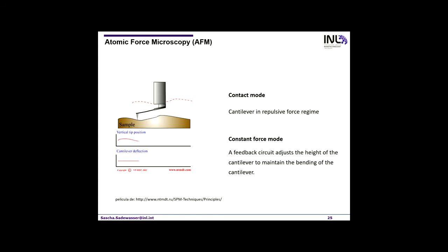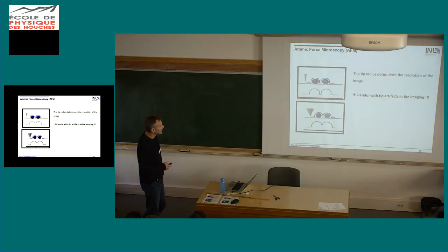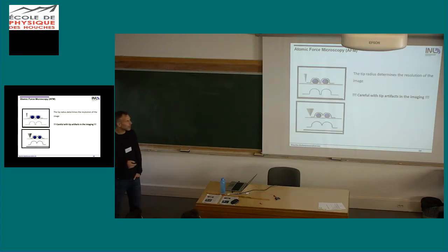And the other option is to go again for feedback. So we feed back to the Z piezo so that the tip bending is always constant. So the cantilever deflection here is constant, and we directly measure the surface topography as the voltage that we apply to the Z piezo. And again, this of course is a bit slower because we need to have this feedback mode. And of course we need to calibrate our Z piezo. So we need to know how much voltage corresponds to which change in Z. But then we get a direct measure of the topography. And of course this is all done by the manufacturers, so there's nothing to do as a user.